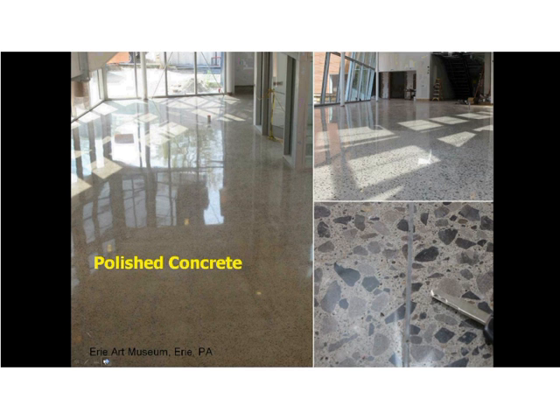For those folks that do not believe that fiber reinforced concrete can be polished, I would welcome you to go visit the Erie Art Museum in Pennsylvania. Typically, though, for macro fibers, and I believe this was a high-volume macrosynthetic fiber dosage, you would need to apply a deeper grind if you wish to have polished concrete. A light grind will most likely expose some fibers that may lay flat at the surface, and they would appear as small lines or streaks. A deep grind, pushing through that top layer of paste, will provide you with the quality of concrete floor that you would be looking for and could achieve even with conventional concrete.